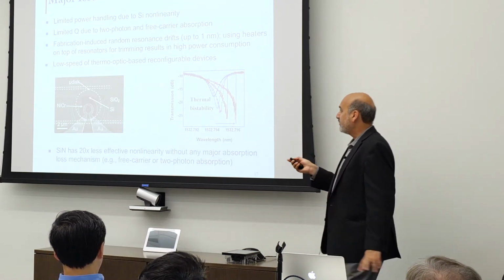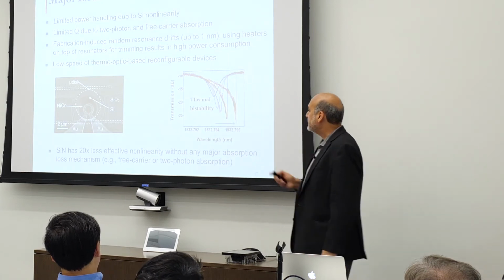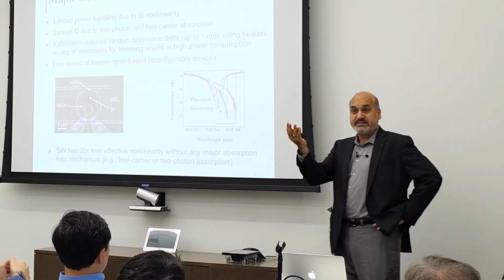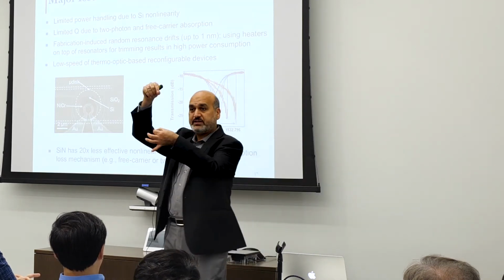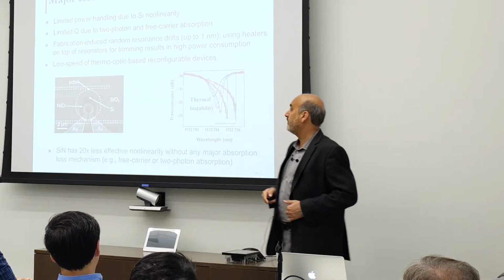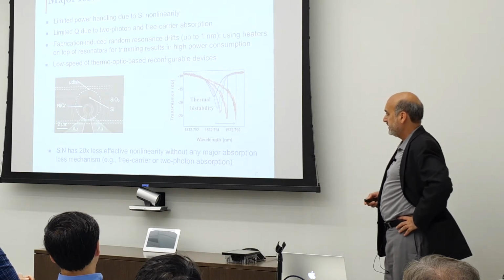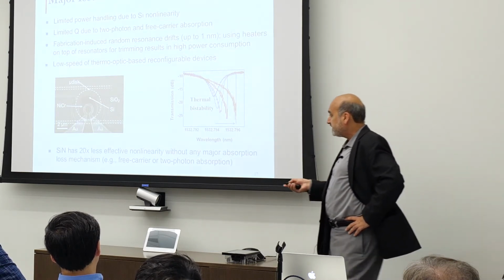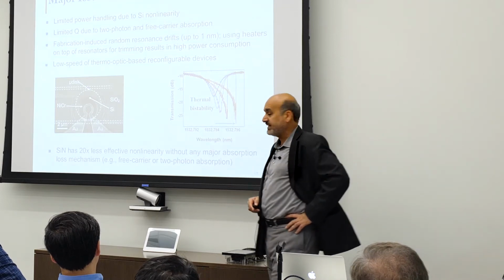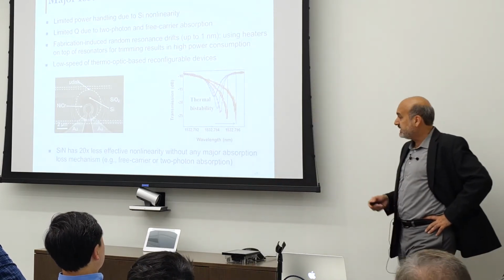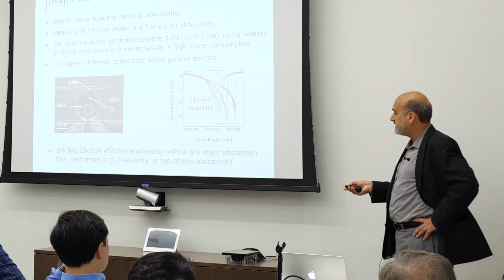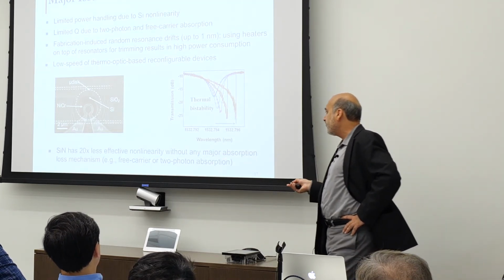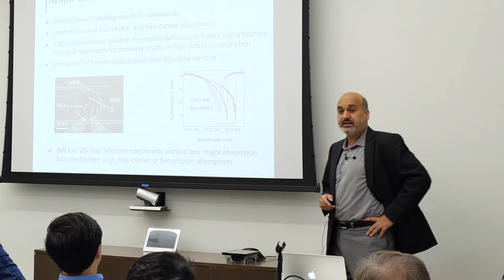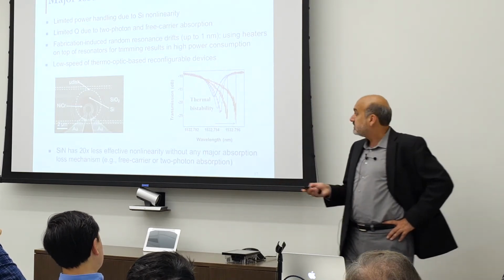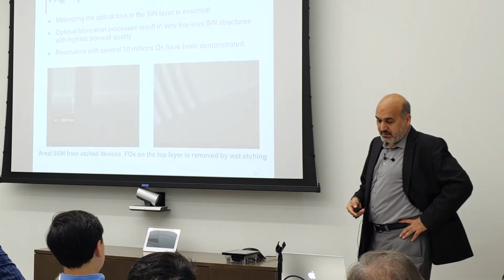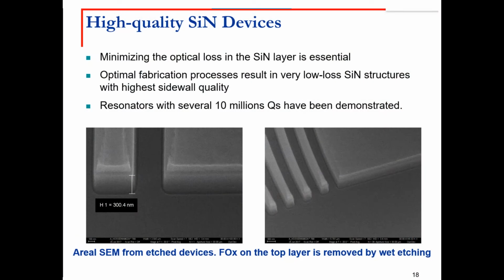And then, thermo-optic based devices are also very good for correcting the wavelengths of a resonator by putting a heater on the top, but usually they are power consuming and also low speed. That has motivated research on silicon nitride over the last decade at least. And the reason is silicon nitride has much less nonlinearity and also very low absorption because it's technically a dielectric material. So there has been a lot of effort in making high quality silicon nitride devices.